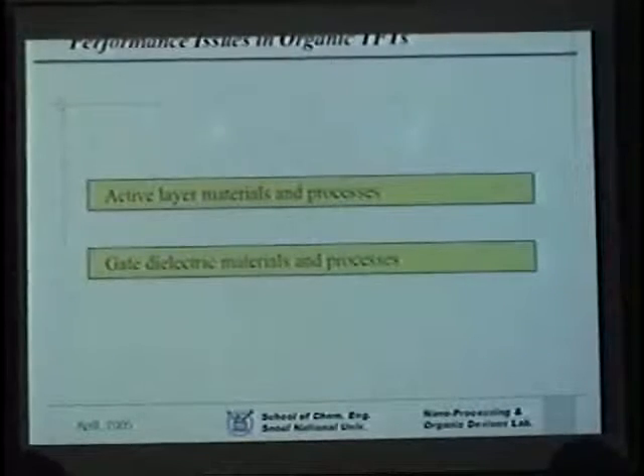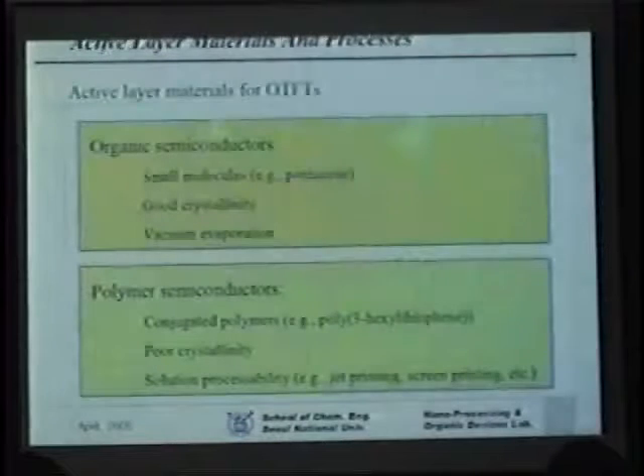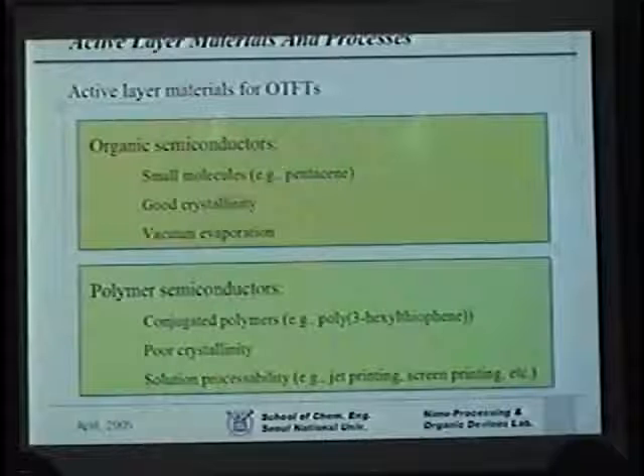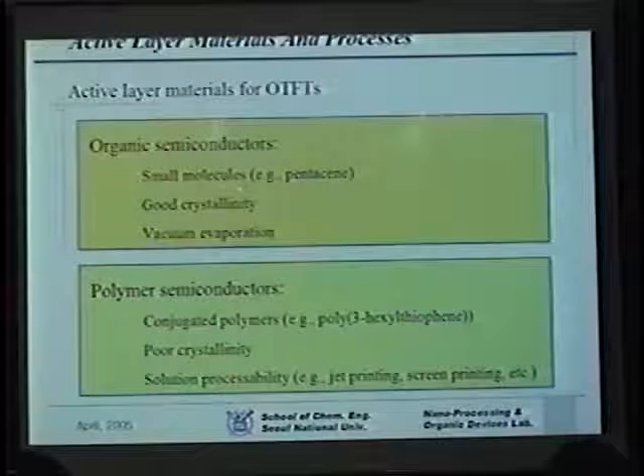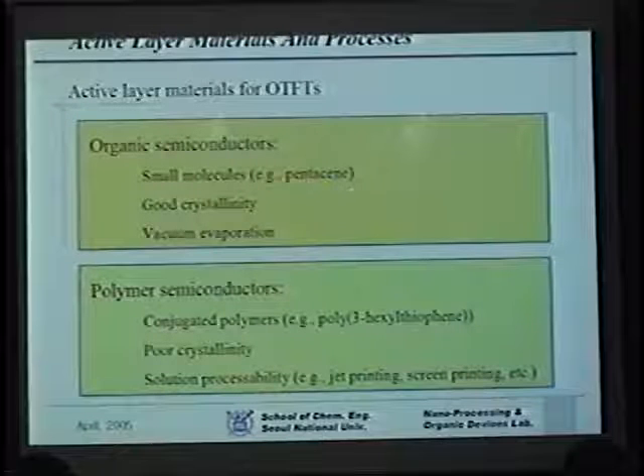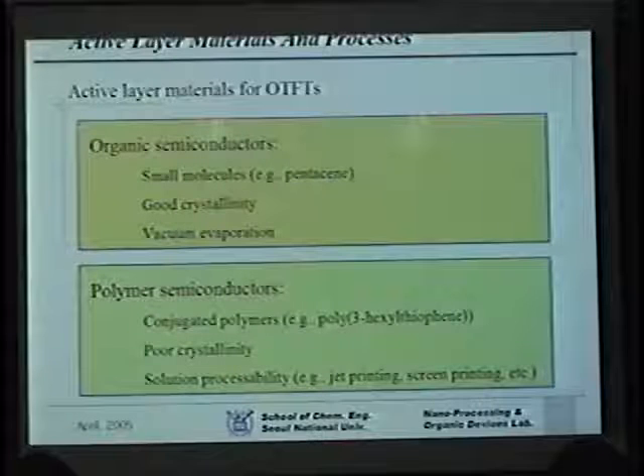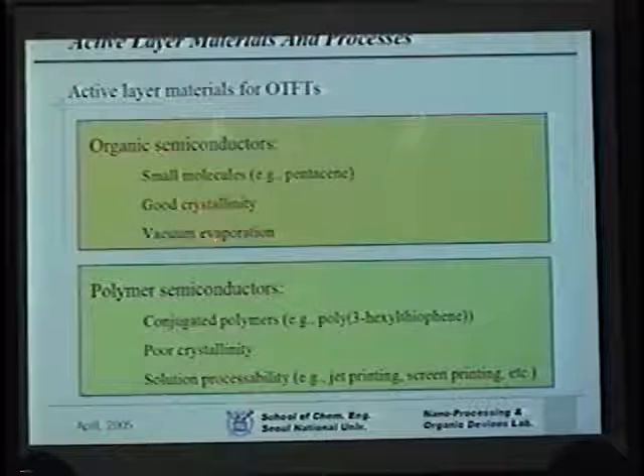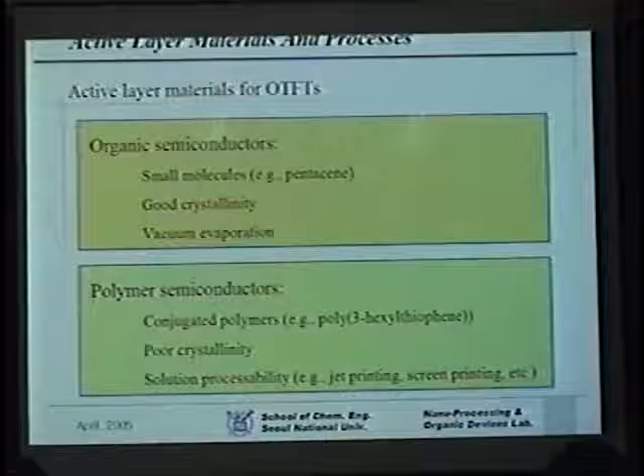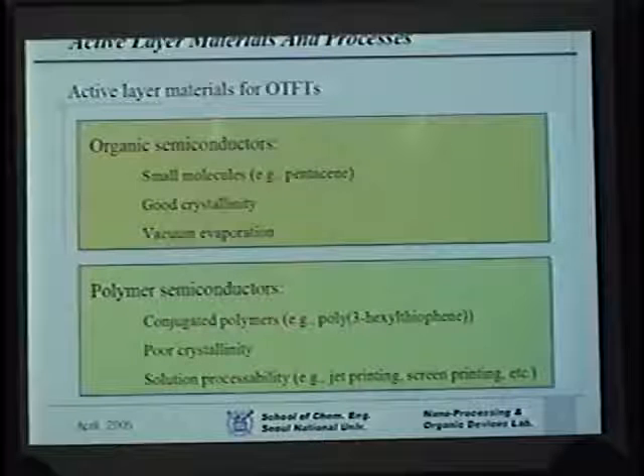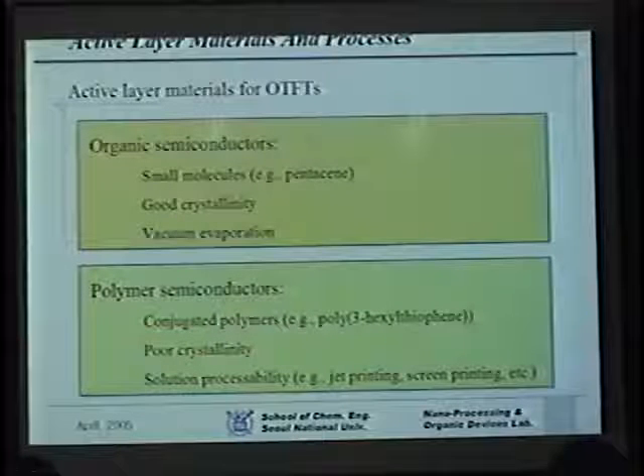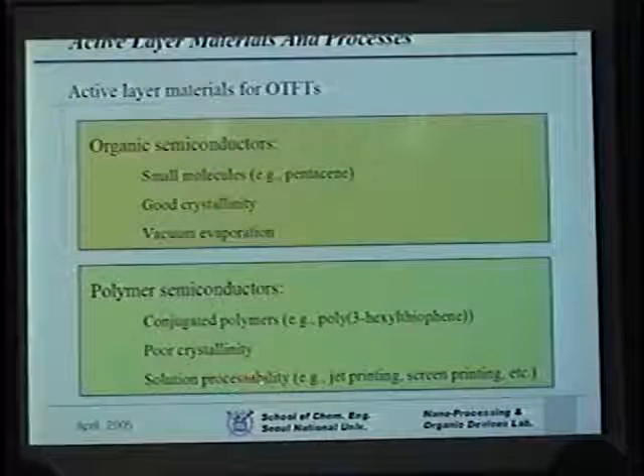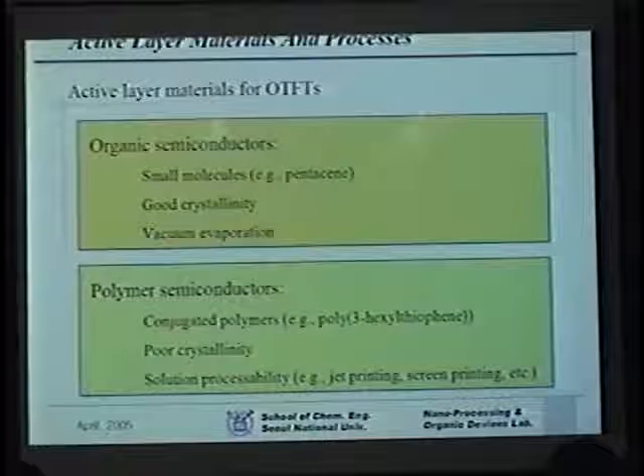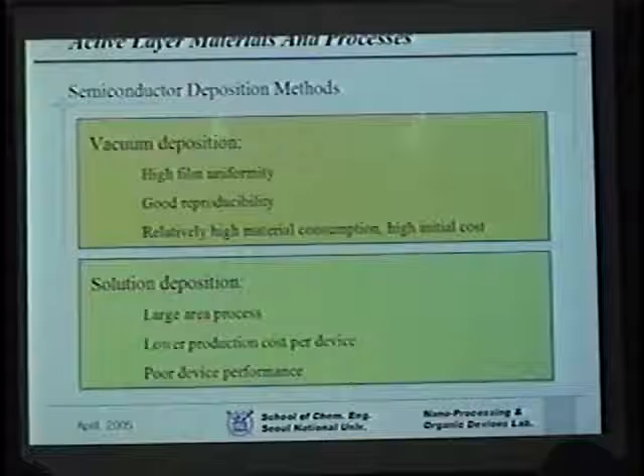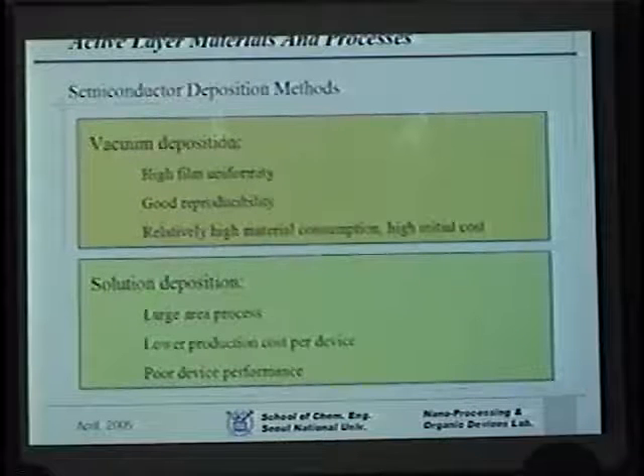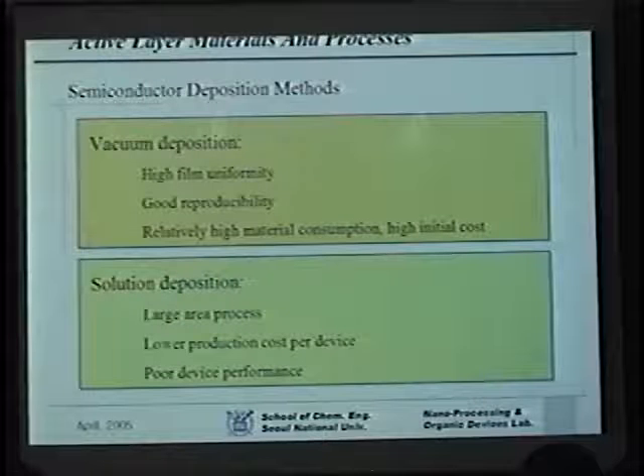Let me just go into a brief review of active materials and gate dielectric materials. As far as active material, for organic semiconductors, typically small molecules are used. The preferred substance these days is pentacene. It will give you good crystallinity, and you do the formation through vacuum deposition. For polymer semiconductors, conjugated polymers are used. Of course, because of the nature of polymers, crystallinity is not that great, but it does give you the advantage of being able to do solution processing, which is cheap. This particular one I mentioned briefly, so let me just move on to the next one.